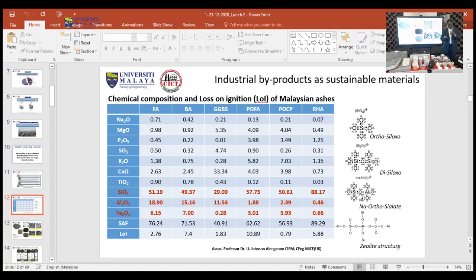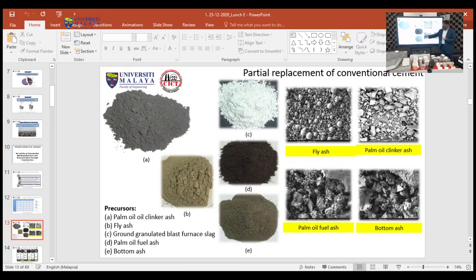Even though some of these particles are not similar to others, like for instance fly ash, which is widely used because of its spherical particle shape and also its pozzolanic and cementitious properties. But other locally available materials, such as locally available fly ash, ground granulated blast furnace slag, palm oil clinker ash, palm oil fuel ash, and bottom ash, could be utilized in future based on the properties and also the durability aspect. That's important.